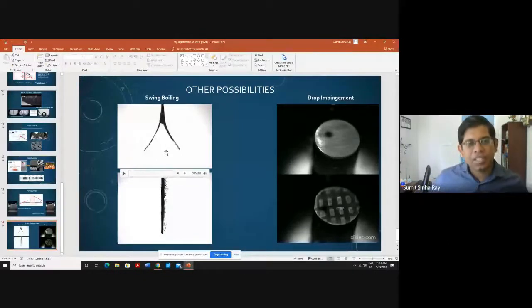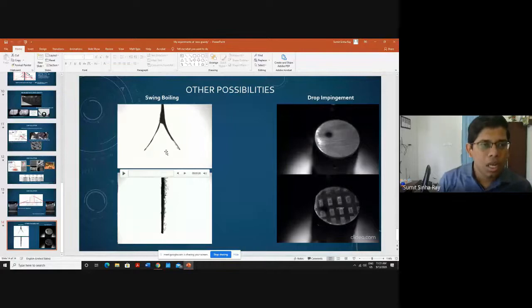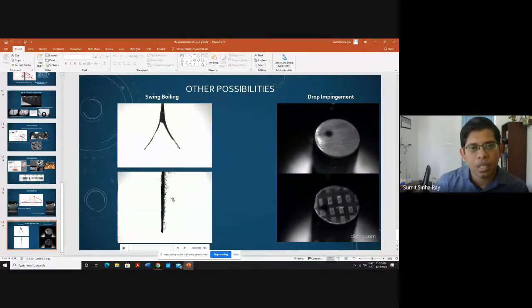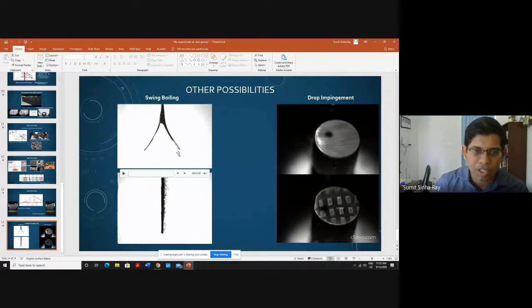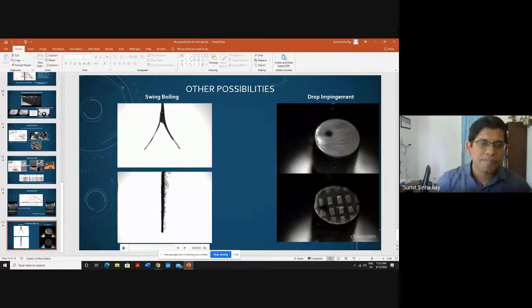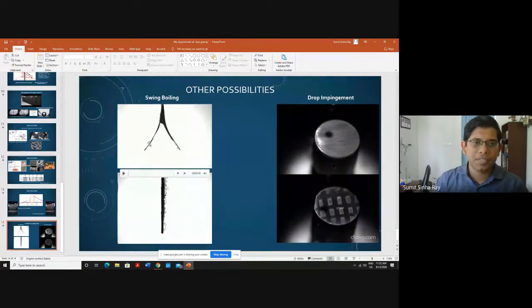When the bubbles leave the surface, it happens in the cases of metal quenching, and you have probably seen it during cooking. Your oil is really hot, and then suddenly one spice jumps out, right? Because one small droplet of water or oil has burst because of the presence of that. So the force with which the bubble leaves the surface is actually drastic. It's quite a lot. What we did was take these two heaters, put them in this dimension, sandwiched together. Once we had sandwiched them together, we switched the heating polarity. So either we heated this surface or heated that surface.